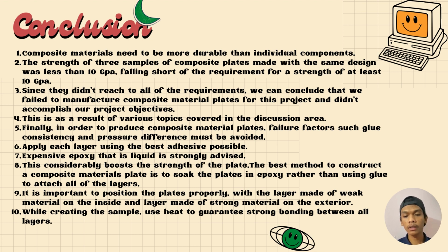Okay, first, composite material needs to be more durable than individual components. Then, the strength of 3 samples of composite plates made with the same design was less than 10 GPa, falling short of the requirement for a strength of at least 10 GPa. Then, since we didn't reach all of the requirements, we can conclude that we failed to manufacture composite material plates for this project and didn't accomplish our project objective. This is a result of various topics covered in the discussion area.